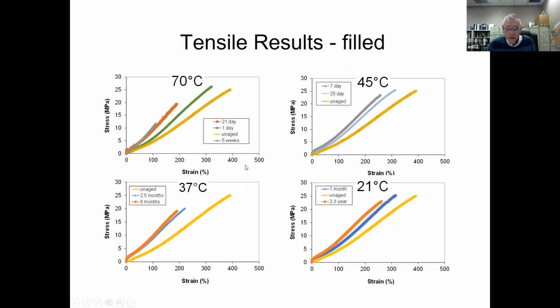37 degrees, and 21 degrees. So here's the unaged, one day, 21 day, five weeks. And then here unaged, 7 day, 25 day. And then we have unaged, 2.5 months, 8 months. And then room temperature: unaged, 1 month, 2.3 years.